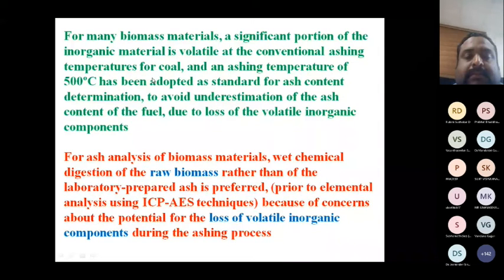For many biomass materials, a significant portion of the inorganic materials is volatile. Here comes a very important point. All the participants, please pay attention. For many biomass materials, a significant portion of the inorganic materials is volatile at the conventional ashing temperature of coal. For coal, we do ashing at 800 degrees. In coal analysis, for proximate analysis and ash preparation, the ash content is determined at an ashing temperature of 800 degrees.